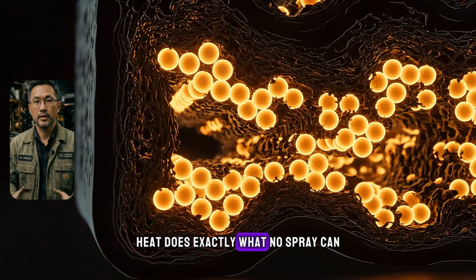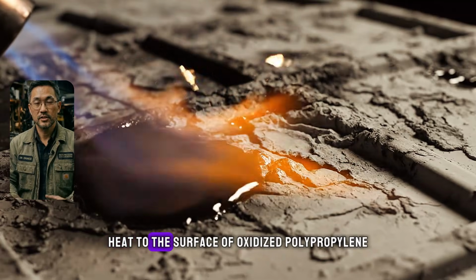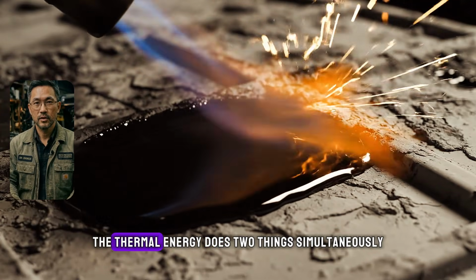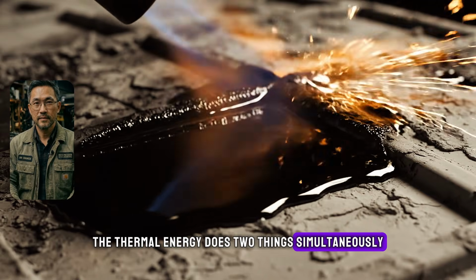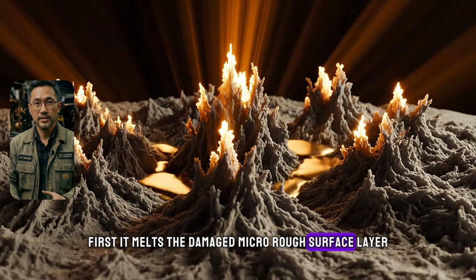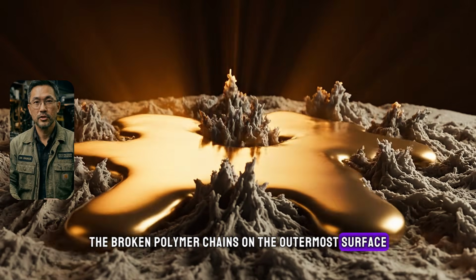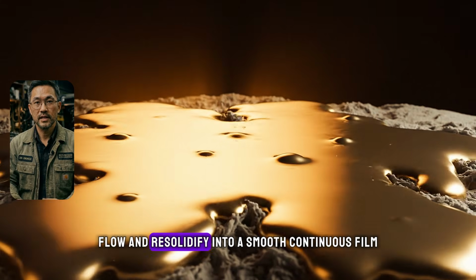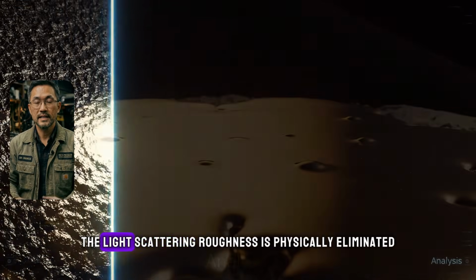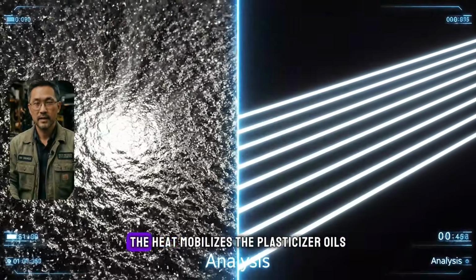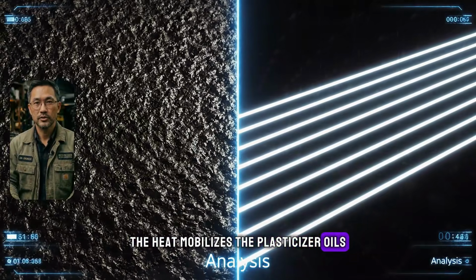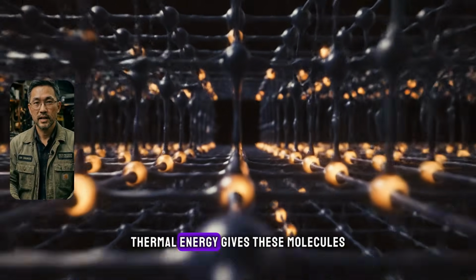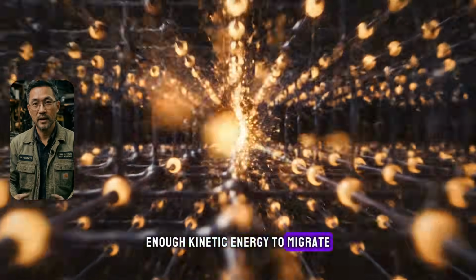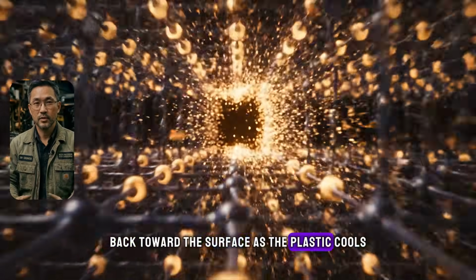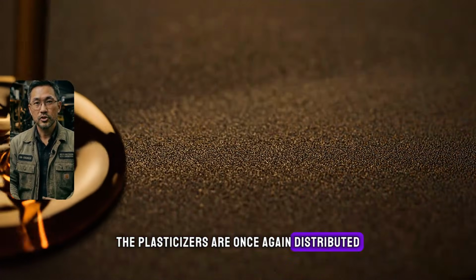Heat does exactly what no spray can. When you apply controlled heat to the surface of oxidized polypropylene, the thermal energy does two things simultaneously. First, it melts the damaged micro-rough surface layer. The broken polymer chains on the outermost surface soften, flow, and resolidify into a smooth, continuous film. The light scattering roughness is physically eliminated. Second, and this is the critical mechanism, the heat mobilizes the plasticizer oils that have migrated below the surface. Thermal energy gives these molecules enough kinetic energy to migrate back toward the surface. As the plastic cools, the plasticizers are once again distributed at the outer layer.